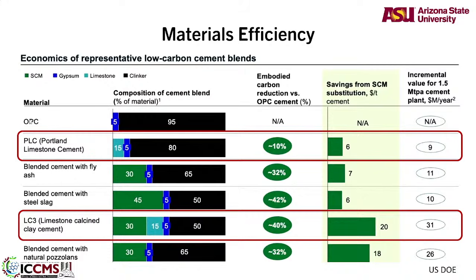So Portland limestone cement is what is picking up, and it's happening in most parts of the world in some fashion. Blended cements with fly ash in India, this is a great option. It still will be a great option. Blended cement with steel slag, I won't even talk about it in the US because we don't have steel slags available. All steel slags are accounted for. We don't really have new steel plants. And even if there are steel plants, they are electric arc furnace slag, no more blast furnaces, right? So you get into trying to solve one problem, and therefore you end up with not enough materials for concrete the way we want to use it. And then limestone calcined clay cements at the bottom.